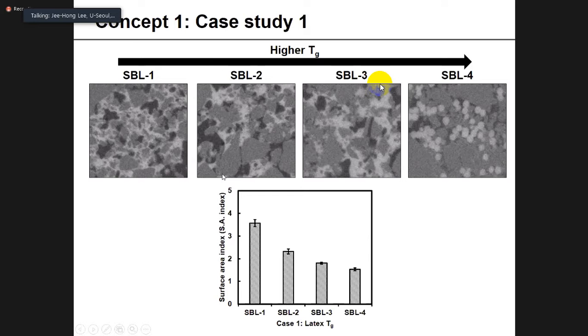If you look at the result, these are parts of actual coating layer images, and this one shows the result of the SA index. You can see that as the Tg of latex elevates, the latex particle maintains its original spherical shape, which does not create much surface area, and you can see that the result is decreasing. So it is successfully presenting, numerically, the dispersion and the deformability of latex within the coating layer.